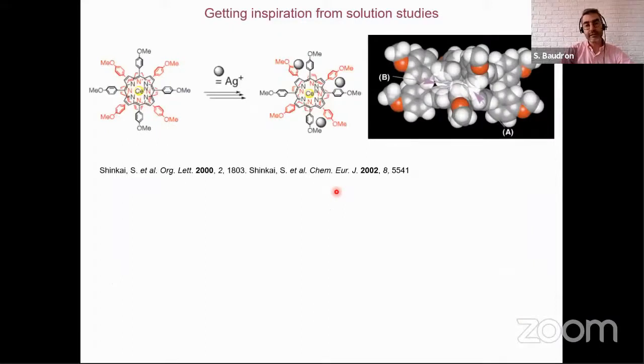So to do that, we went back to the original solution studies that I mentioned earlier. In the solution studies by the group of Seiji Shinkai, they had studied this double-decker cerium porphyrin system and its assembly with silver 1 cation. And they had this one representation of this compound, and they showed what they called the B pocket, which corresponds to two pyrrolic systems that are facing each other and would favor the silver pi interaction. And we thought, maybe naively, that having two pyrrolic rings arranged in such a fashion, maybe we could favor the silver pi interaction in this case.